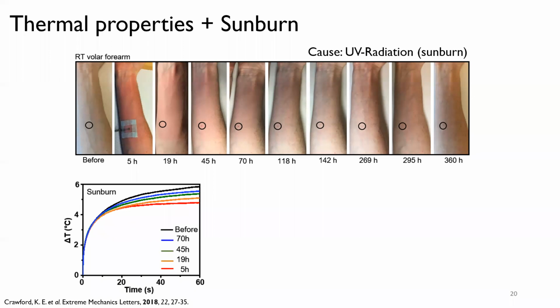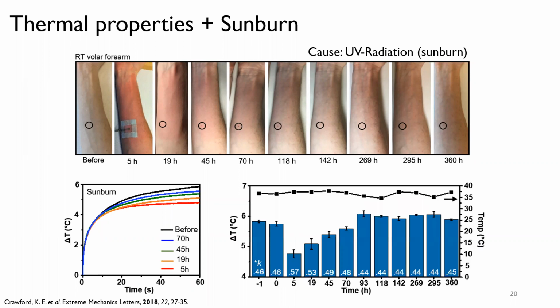But then if you look at the next line, the red line, you have a much lower change in temperature. And that's because we have more blood near the surface of the skin. Blood has a higher thermal conductivity, so it's more effective at dissipating heat. And second, we have mass transport of heat from blood flow away from the system. And so we can measure the effective, not an exact, but effective thermal conductivity value, taking those differences into consideration.